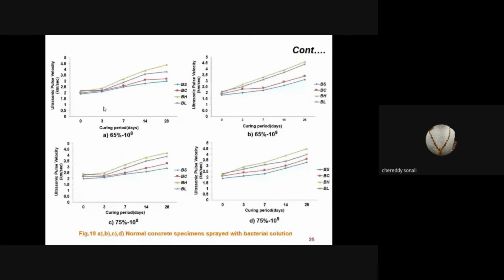Means this bacteria is precipitating calcite crystals, which heal the pores and also cracks in the concrete, represented by the increase in UPV values. As the UPV values go on increasing, it represents that the number of voids, cracks, or pores goes on decreasing. As these UPV values are low, it means there are a number of cracks. From this image, we can clearly say that more healing rate was found in the Bacillus halodurans solution sprayed concrete specimens.